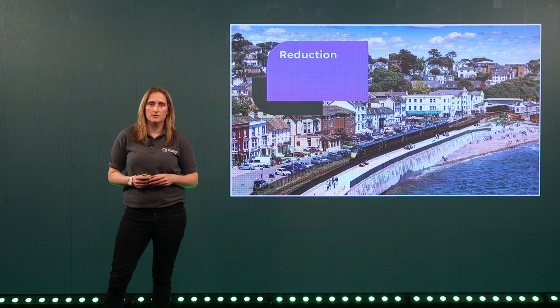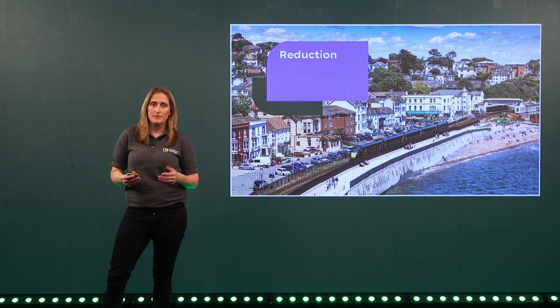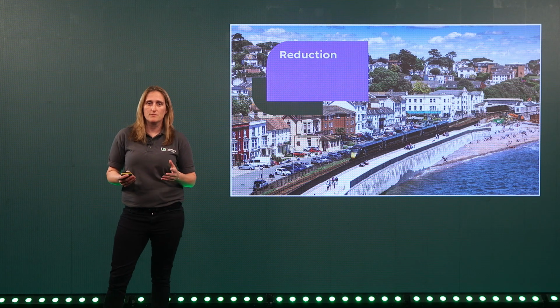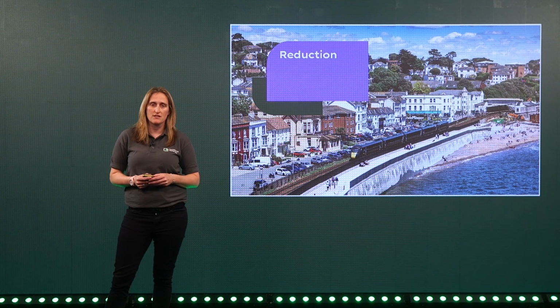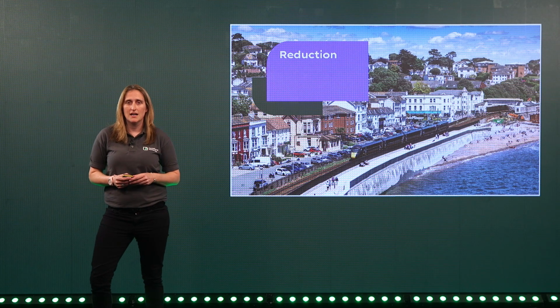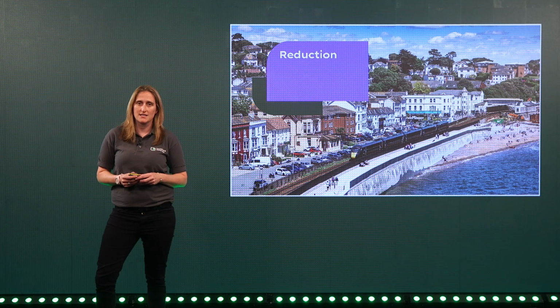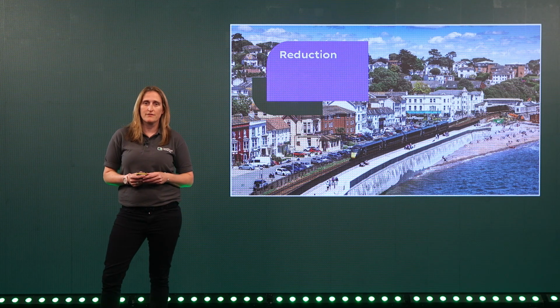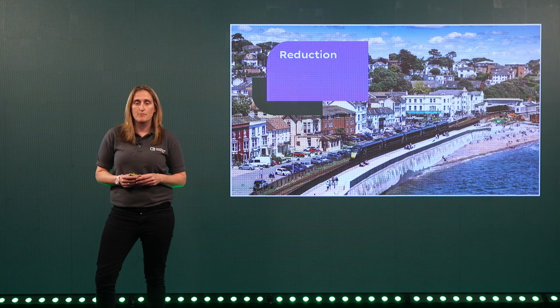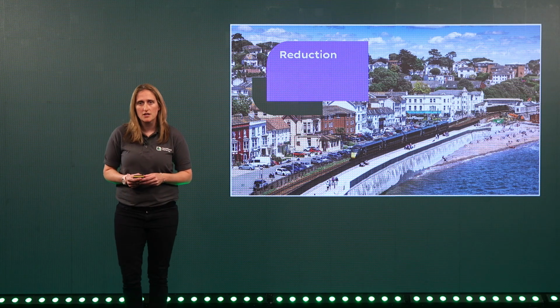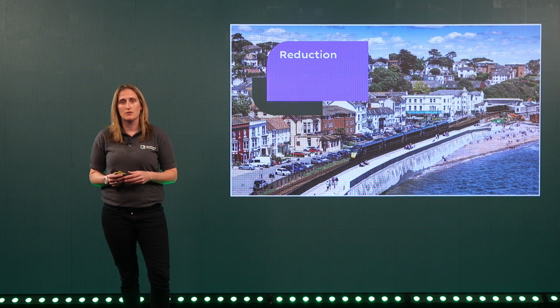Asphalt is 100% recyclable. Using recycled asphalt planings, or RAP, in the asphalt production process avoids using virgin aggregates, protecting natural resources for future generations. It also reduces the use of bitumen, supporting the circular economy and reducing carbon emissions. Our concrete-placed asphalt contains additives derived from waste plastics. It is produced at a low temperature using our energy-reduced asphalt warm mix process, which is mixed at 40 degrees lower temperature. We use chemically modified waste plastics comparable to bitumen without compromising performance, and this prevents the plastic from going to landfill. Recycled plastic can also be recycled back into new asphalt at its end of life.